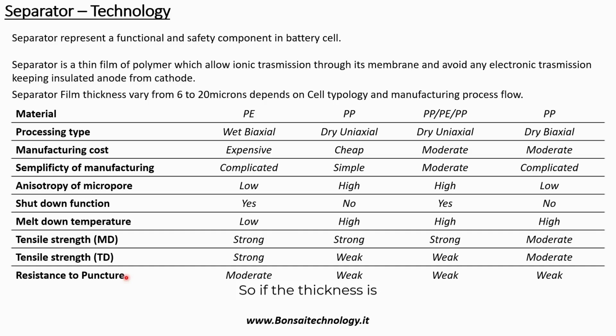So if the thickness is thick enough, we can say, to prevent the particles, the contaminants, from passing through the separator, there's no risk of creating a short circuit. But again, it's not possible to have a super thick separator, because the separator is not giving any benefits in terms of energy density. Its only function is to insulate the anode from the cathode. So if we have in our cell a big volume represented by the separator, this volume is not giving us any cell capacity, any energy. So we need to find a compromise between separator properties, separator thickness, and safety.